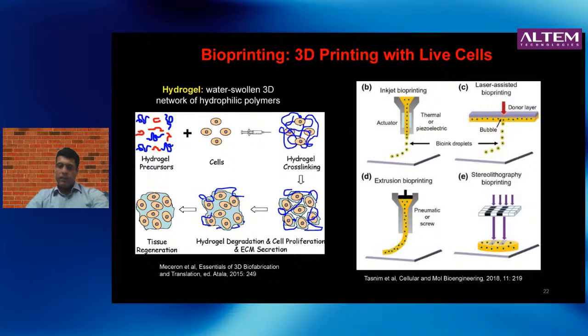Also, the other technology that is coming up in a big way is the stereolithography based printing or digital light based processing technology. So here there is actually nothing that comes out of a nozzle. Here you have a vat or a bath of pre-polymer solution which is sensitive to light, and you shine a light source at particular locations. When you do that, in that particular location, the polymer gets cross-linked, because these are photosensitive polymers. The cells are trapped in the gel, and you will end up creating a cross-linked gel in this bath itself. So I'll give you some examples of this particular technology of DLP printing, which we've been trying to use in the last year and a half or so.